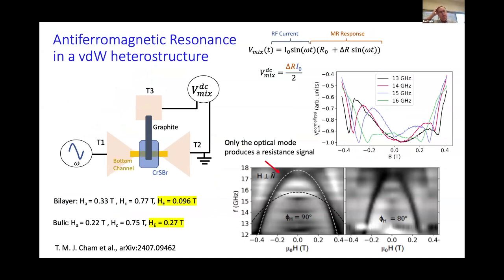Okay, so how do you measure the high frequency dynamics? Well, we use an offshoot of spin torque ferromagnetic resonance. We'll apply a high frequency AC signal through the bottom channel that will excite the antiferromagnetic dynamics both through Oersted fields and possibly with some contribution from spin-orbit torque. Then we'll detect the dynamics by having some AC current going through the tunnel junction that will mix with the resistance oscillations and give us a resonant peak at a DC voltage. So just looking at the raw data, once you've worked out the microwave engineering, you see resonant dips here due to this DC mixing signal at both positive and negative field, corresponding to when the magnetic resonant dynamics are resonant with the applied AC field.